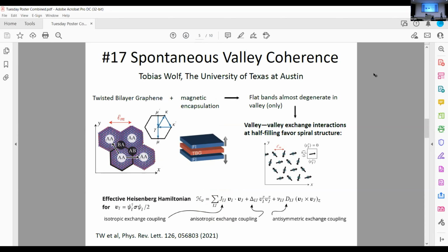Hello, everyone. I'm a new postdoc in Allan MacDonald's group at UT Austin. On my poster, I will present some results on spontaneous valley coherence in twisted bilayer graphene, as shown there on the left, encapsulated by ferromagnetic insulators, shown right next to it. Remarkably, this system can have flat bands that are degenerate in valley, but non-degenerate in all other degrees of freedom. This makes valley-valley interactions extremely important and can lead to non-trivial valley mixed states, as depicted with these cute arrows there. So we find such a state in the system, and we explain it in terms of some effective valley-valley interactions. Please stop by if you're interested to discuss it.